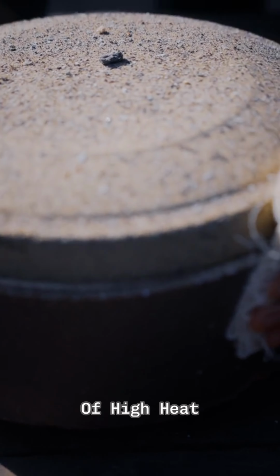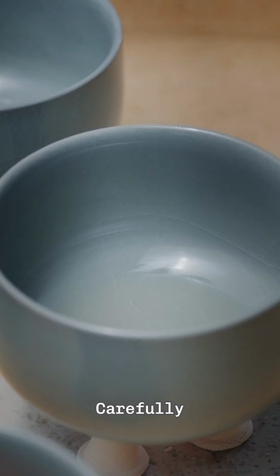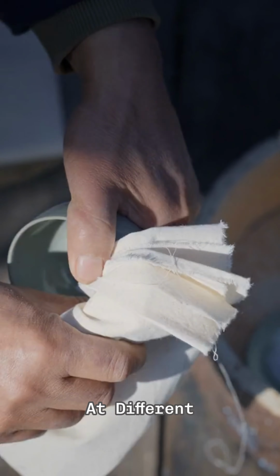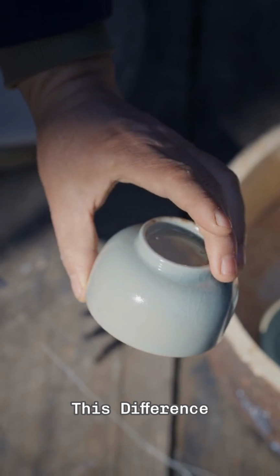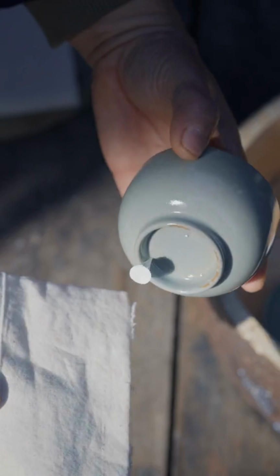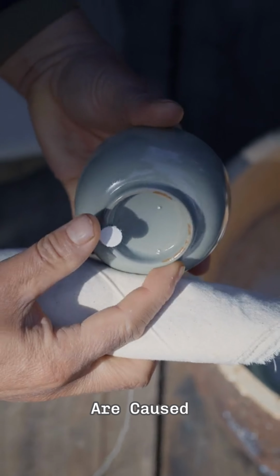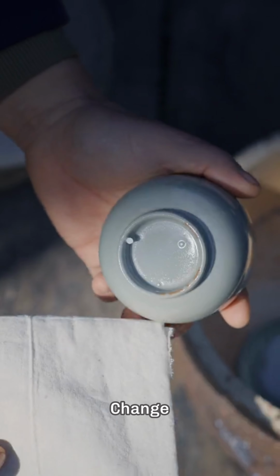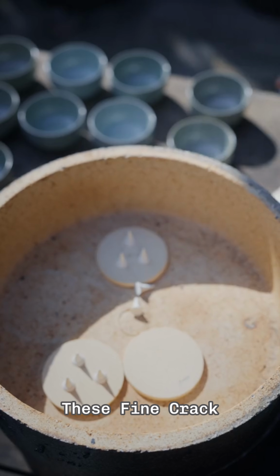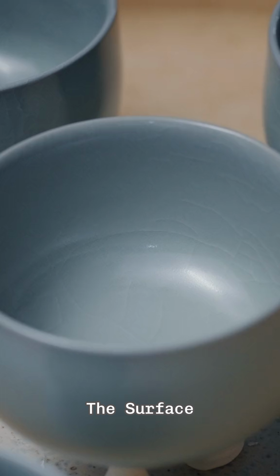After hours of high heat, the kiln is opened carefully. As the bowl cools, the glaze and the clay body shrink at different rates. This difference creates tension on the surface. The cracking sounds you hear are caused by the glaze adjusting to the temperature change. These fine crack lines form naturally across the surface.